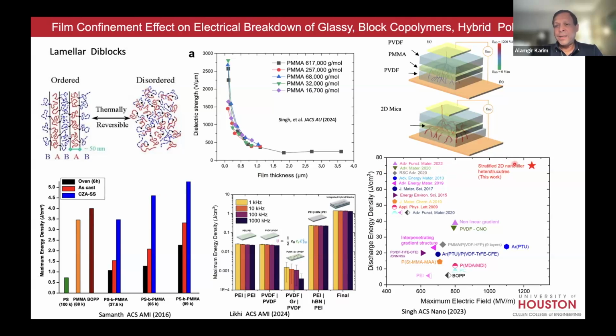So it's behaving like a real energy storage device. If you look in the literature, all these advanced materials and other high impact papers, the maximum was around 35. I'm talking non-ferroelectrics. Ferroelectrics go higher, but they lose a lot of energy. So you see, we are more than double the sort of world record for the non-ferroelectrics at this point, simply by inserting a 2D ceramic sheet at the interface.